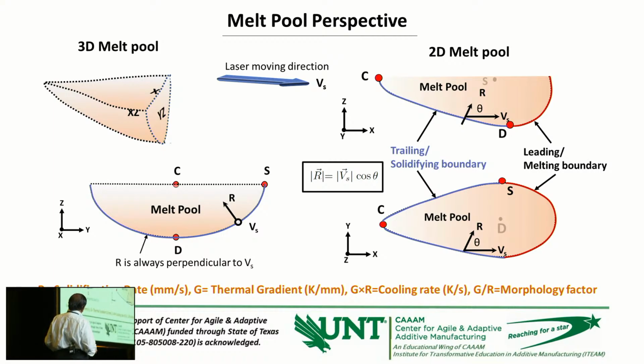So for example, your laser is moving. There are a 3D depiction and a 2D depiction of the melt pool shown here. The laser is moving in this direction. The velocity V is the velocity of the laser beam direction. Laser beam motion speed is given by V, and R is the solidification rate. So R is connected to the laser moving direction by this equation: R equals V cos theta, where V is the laser moving speed. So the grains will grow in that direction.